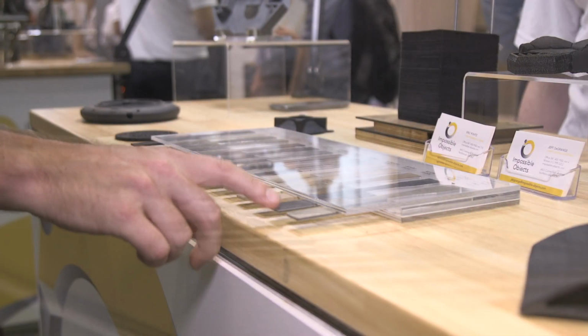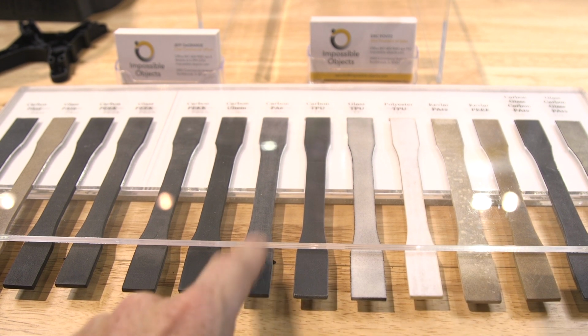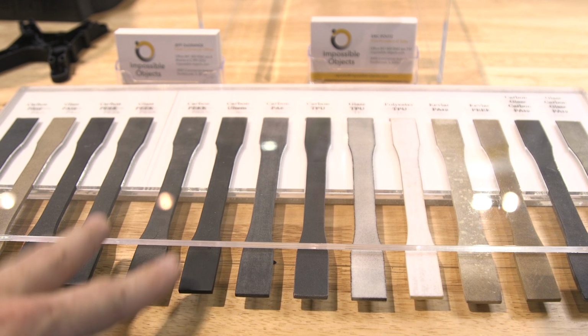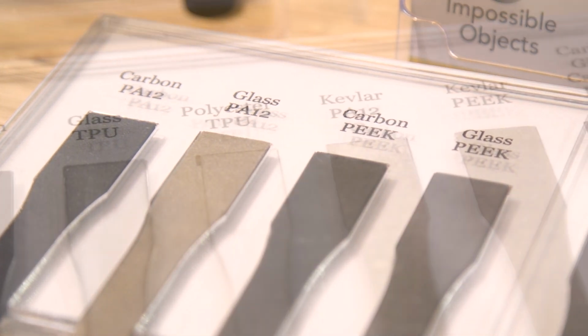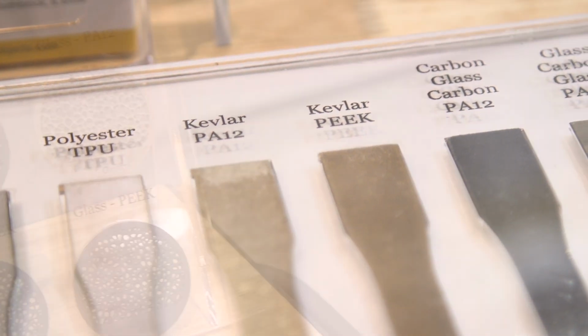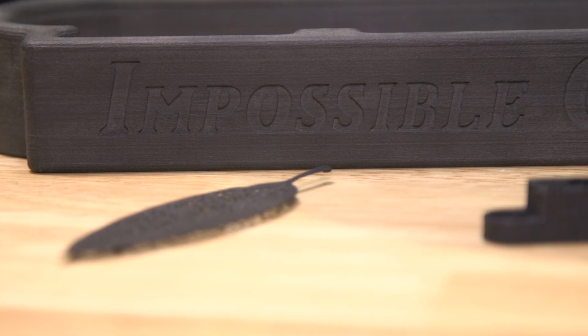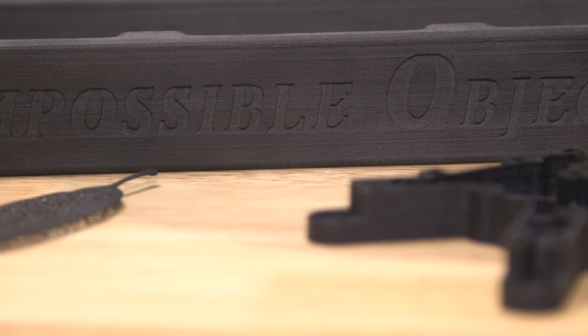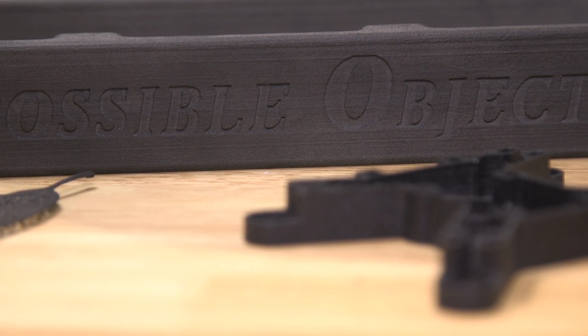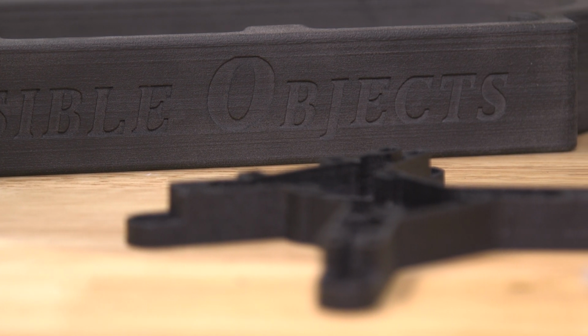Thirdly, we have a much wider variety of materials. So for substrates, we can use carbon fiber, Kevlar, fiberglass, polyester, and we can use pretty much any thermoplastic. So for low-cost materials and high-volume materials, we can use materials like polyethylene and polypropylene, very low-cost materials. Our material selection is enormously greater than, for example, the sintering processes. They can't, for example, use something like nylon 6 because the melting point is too high for their equipment. That's not a problem for us. So we have a number of advantages over the conventional techniques.